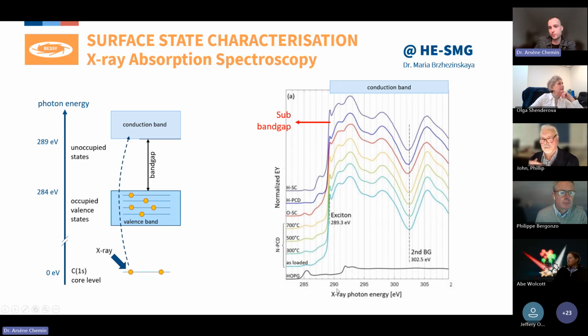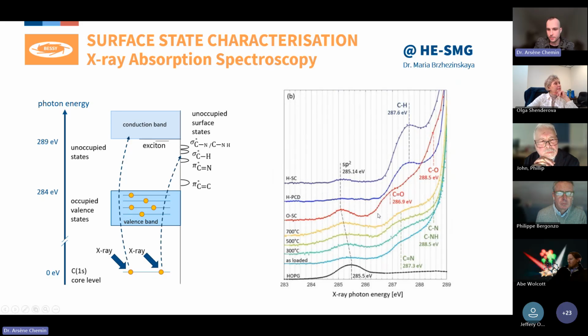If you look at the absorption of diamond material in the X-ray, you generally find this kind of spectrum, with a very strong absorption starting at around 289 eV, which corresponds to the excitation in the conduction band. You also find a second dip at about 302 eV, which corresponds to the second band gap of the diamond, where the density of unoccupied states is actually lower. And in the case of very nice crystalline diamond, you have this sharp peak here that corresponds to the exciton of the diamond at